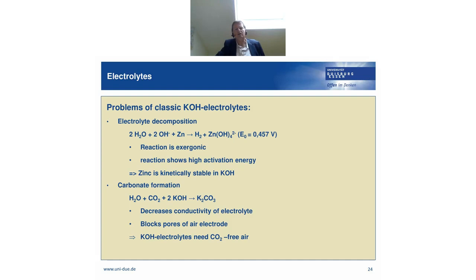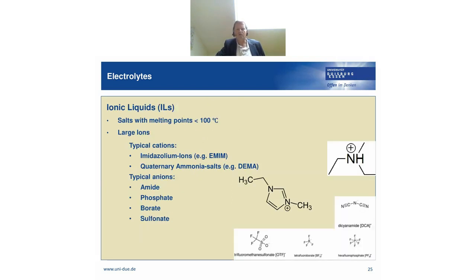But even in our alkaline electrolyte, we have some hydrogen evolution, and especially this is also temperature dependent. In summer, when we have higher temperatures in the lab, we have more gas evolution. And of course, carbonate formation is a well-known problem for the alkaline electrolyte. CO2 is taken up from the atmosphere, and then potassium carbonate forms and blocks the pores of the air electrode. So this was a motivation to look